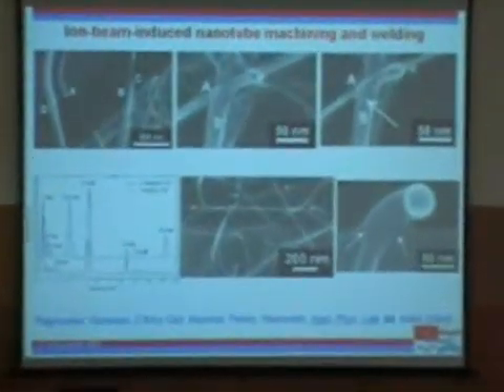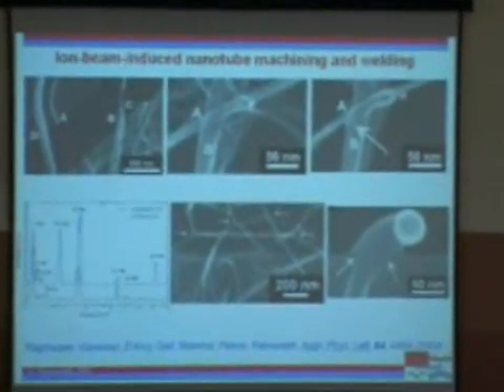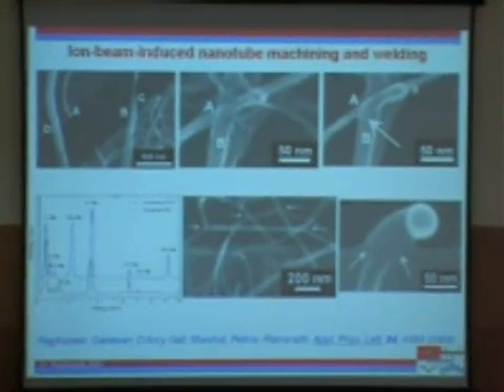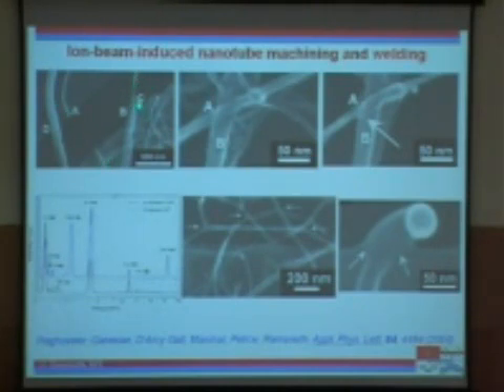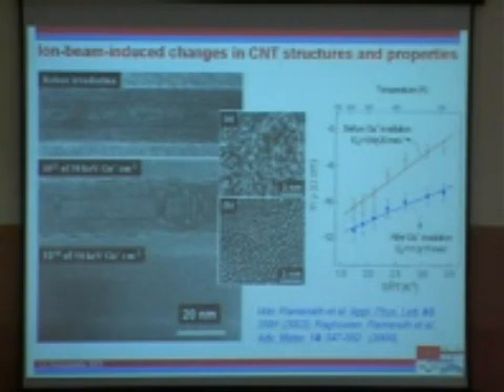Okay, I told you that we wanted to modify nanotubes in a mild way rather than in a very haphazard or very aggressive way. But we need to be careful, and I just wanted to show what ion beams can do. You can see that they can cut the nanotubes, or they can thin them, or do nothing to them, depending upon what the diameter is. In addition, you can also weld them. Here are two proximal nanotubes, and you can see that they are welded over here. All right, and you have multiple welds over here. So your ion beams can also be used as a tool to create networks of these nanostructures. And that would be useful for creating architectures.